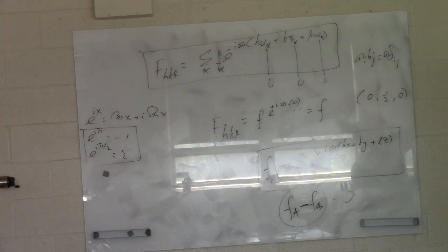But in the case of potassium bromide, since Fa and Fb are not equal, things that you don't see here, you will observe here. You can see these peaks, but there are some additional peaks like 311 and some peaks like 111, right?